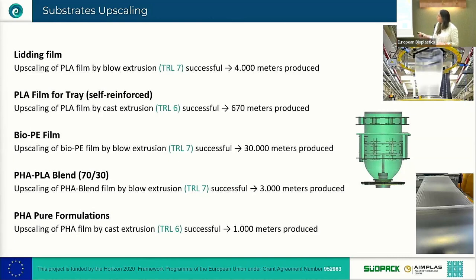As you can see here, we produce successfully at TRLs between 6 and 7 PLA films, self-reinforced PLAs. As I said, for bio-based solution, we have to be innovative, to be smart. How can we overcome the mechanical properties that sometimes are not comparable with fossil-based, and that's why we work with self-reinforcement here. Also, we successfully produce 30,000 meters of bio-based